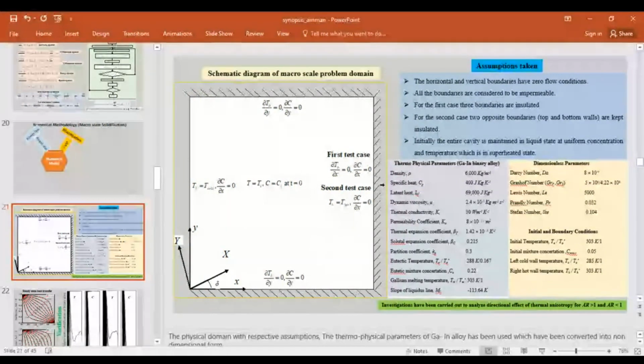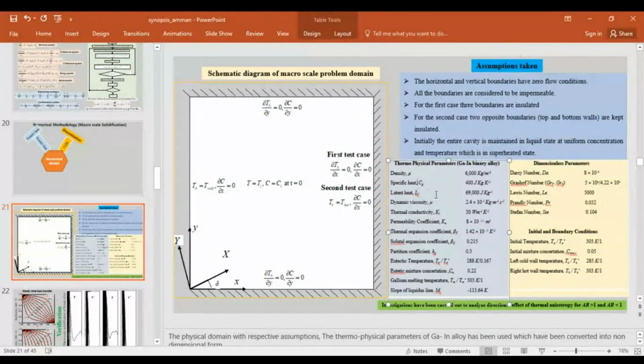And for the second test case, the left wall is maintained at a fixed hot temperature. Like it is mentioned here, for the first test case, three boundaries are insulated. For the second test case, two opposite boundaries, top and bottom walls, are kept insulated. So the entire cavity is maintained in a liquid state at uniform concentration and temperature, which is a superheated state. So the density I have taken for the gallium indium binary alloy: rho is 6000, Cp is 400, Lf is 89,000 joule per kg. Viscosity is 2.4 × 10 to the minus 3. Thermal conductivity is 30 for the liquid.